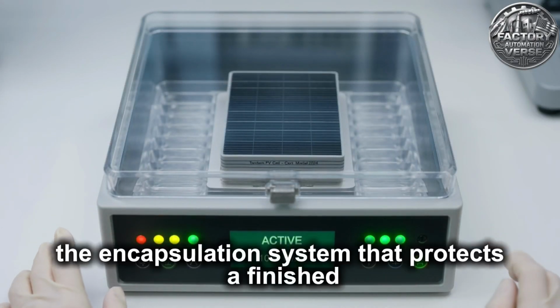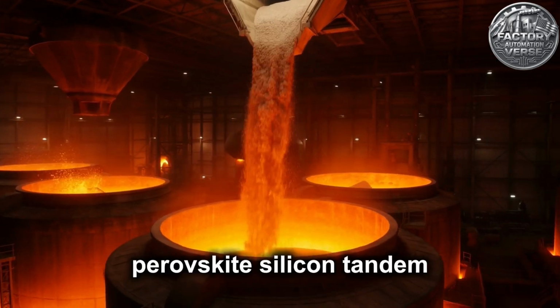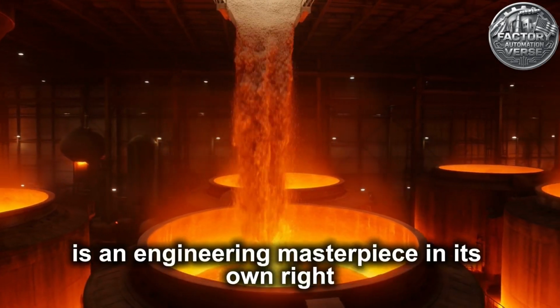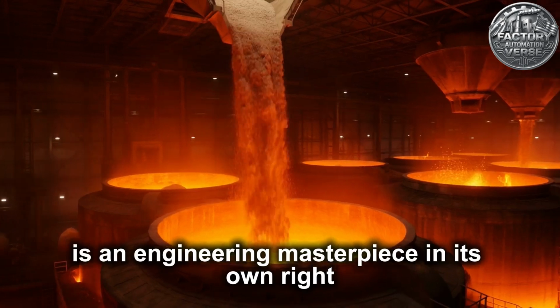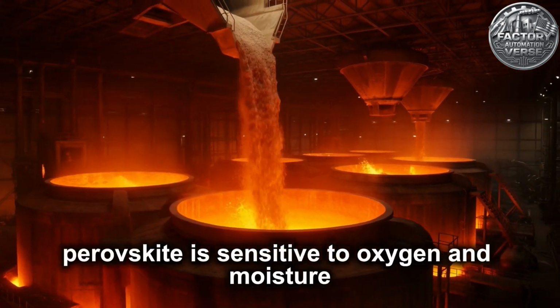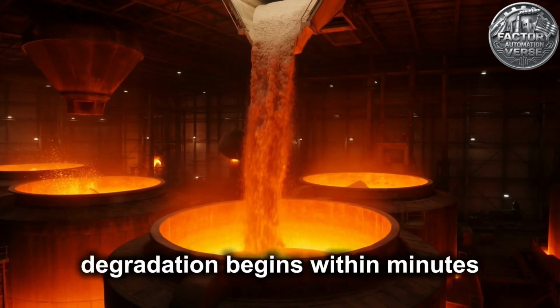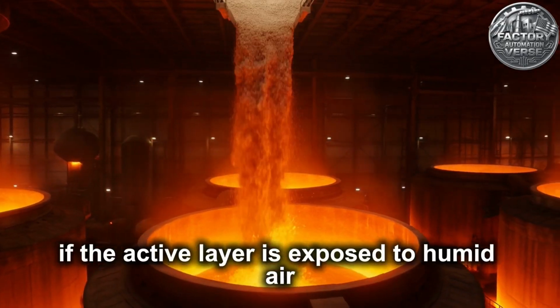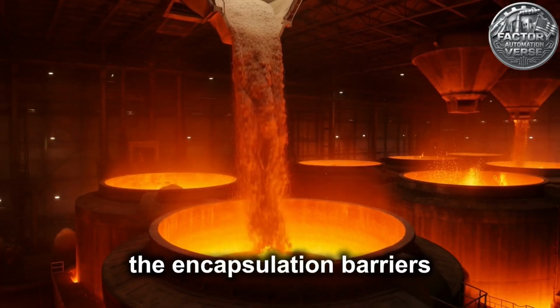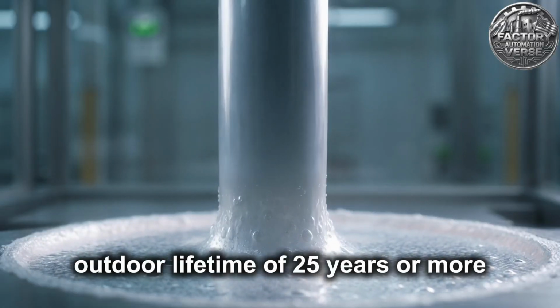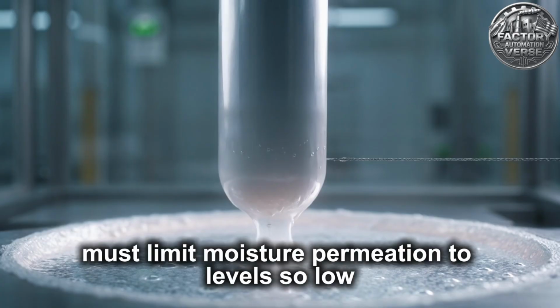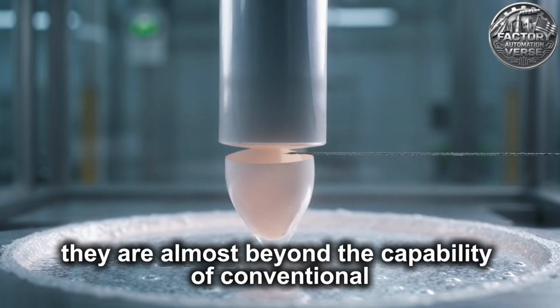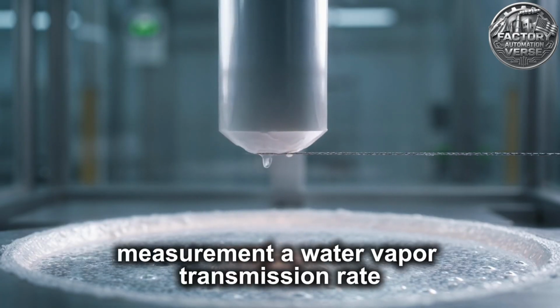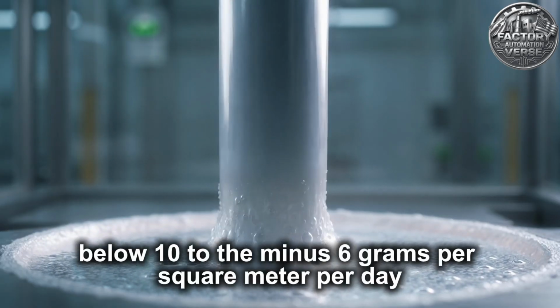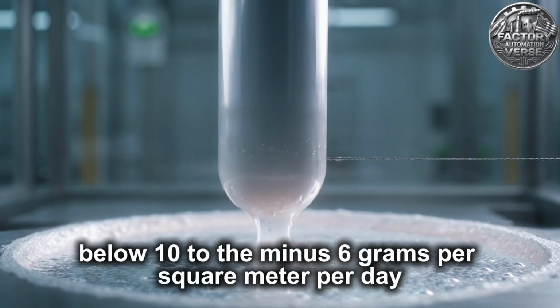Now for the most impressive part. The encapsulation system that protects a finished perovskite-silicon tandem flexible cell from the environment is an engineering masterpiece in its own right. Perovskite is sensitive to oxygen and moisture. Degradation begins within minutes if the active layer is exposed to humid air. The encapsulation barriers required to achieve a commercially viable outdoor lifetime of 25 years or more must limit moisture permeation to levels so low they are almost beyond the capability of conventional measurement, a water vapor transmission rate below 10^-6 grams per square meter per day.